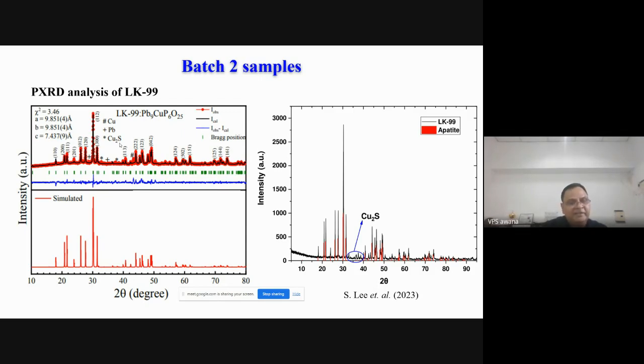We could get a very reasonably good X-ray diffraction, because when we compared with the Cu2S at the right side, which is shown there, even the LK99 by the Korean team has a good amount of Cu2S. Our sample looks good till that date. In fact, now even a better sample has come, last week on 14th of August. I think Bechhöfer has got a single crystal from the Max Planck Institute Stuttgart. So by that time, this was looking to be one of the best samples we could get and was better than the LK99.